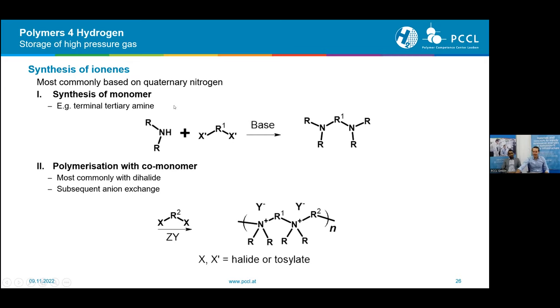So here, just a very short overview of the general synthesis, how we create those polymers. It can basically be divided into two steps. You synthesize a monomer, or some would also be commercially available, here as the example with a nitrogen atom. You let this nitrogen atom react with some dihalide, and here you can choose basically any groups you want. So it gives you a lot of freedom for the structure of the polymer, and you create this monomer with two tertiary amines, which can then, in the next step, be polymerized with a different or the same dihalide. In this process, the amine gets quaternized, so ionically charged. It has a positive charge.